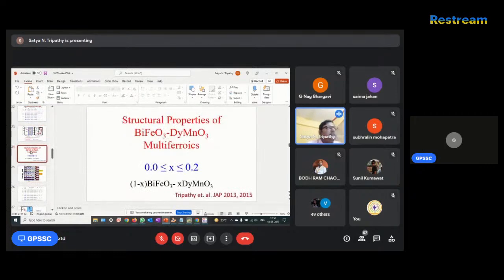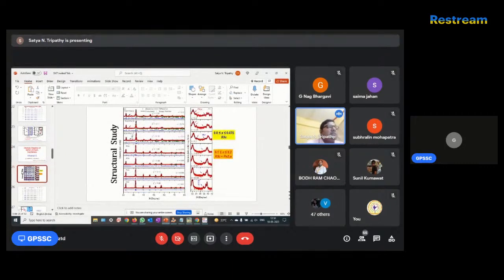Okay, so the next data I am going to show you is basically the same system, bismuth ferrite, but with dysprosium manganite. This paper I think we have published in JAP 2013, 2015, and again in 2017. This is a very good paper, and here also we have the same XRD pattern. We have refined the crystal structure of this system as R3C up to 0.075. After that, we have used the Pn21 space group. So we have done the dual phase refinement.